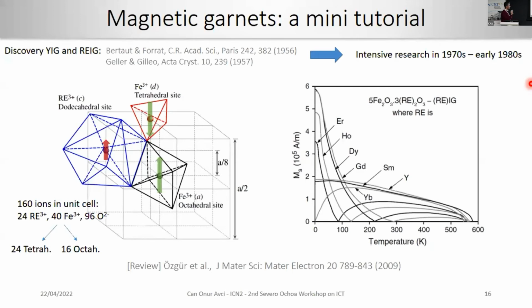Just briefly to give you an idea, the unit cell is actually a complicated one with 160 ions, but in a simplistic way, it consists of tetrahedral, octahedral and dodecahedral sites, and the spins are coupled in the way that I show you here. You have the iron that are coupled anti-parallel due to the super exchange interaction, and you have the third element here, which could be a magnetic rare earth element that couples anti-parallel to that tetrahedral site. Because of the flexibility of choosing this dodecahedral site element, we could choose it from a magnetic or non-magnetic rare earth material.